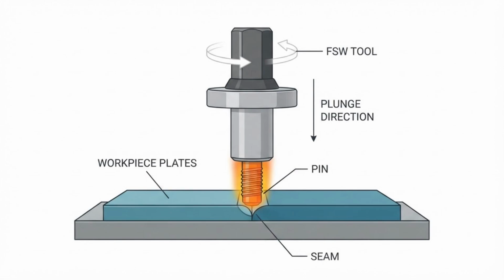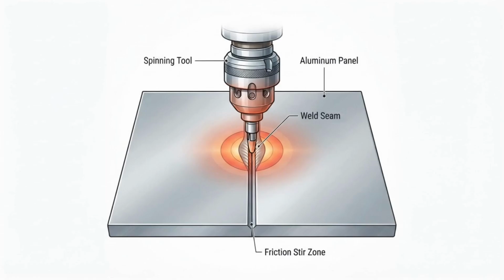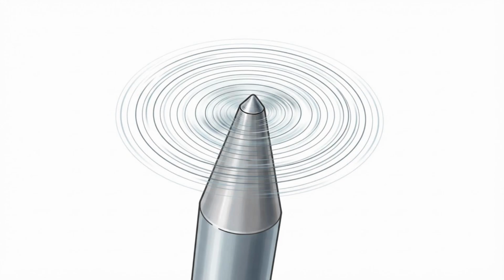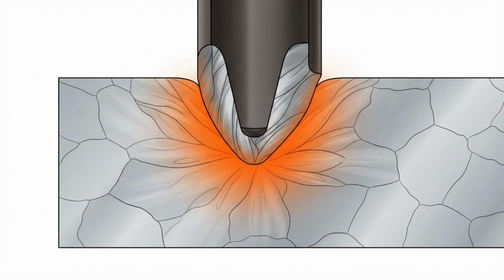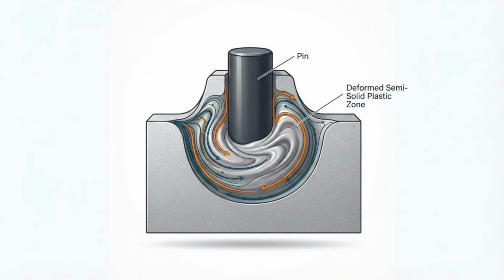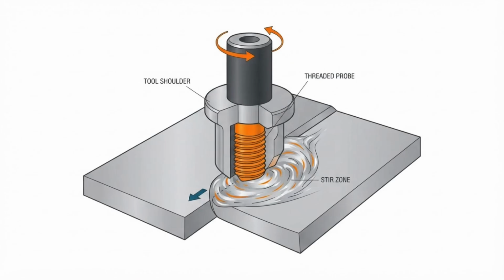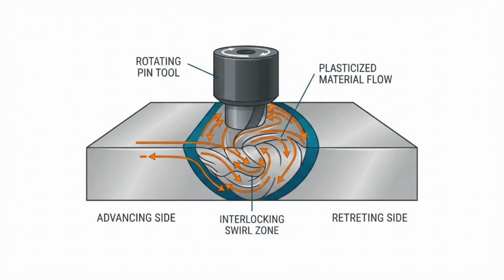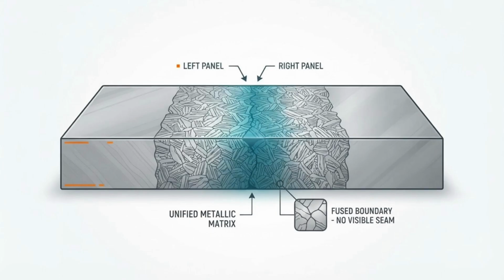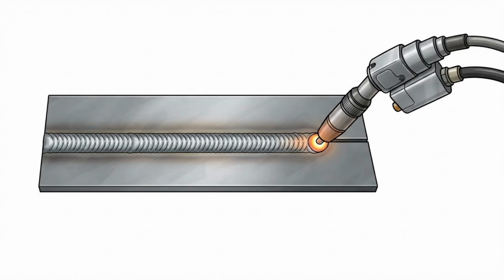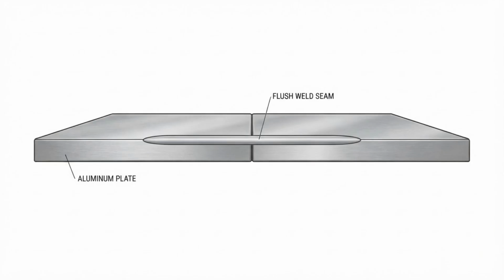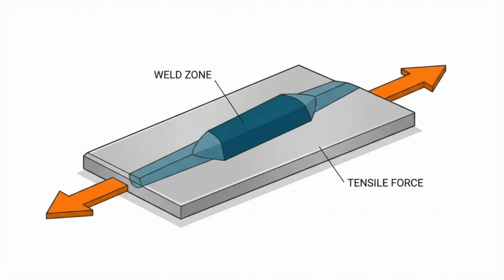A spinning, incredibly hard cylindrical tool is plunged into the seam between two closely fitted aluminum panels. As the tool rotates at high speed and travels along the joint, the immense friction heats the aluminum until it becomes a soft, pliable plastic state. The spinning tool physically churns and mixes the metal from both panels together, forging a continuous, seamless bond as it cools. The resulting weld is flush, perfectly smooth, and often stronger than the surrounding metal.